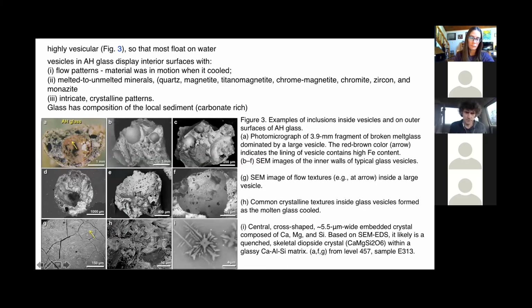What I would like to point out is that on some of the smooth surfaces, very often you can see a kind of lineation that shows there was actually motion of the fluid at the time of solidification. In some of these vesicles you can see coarse crystals growing, probably when the melt was evaporating; there was a lot of gas, and from the gas you could form crystals. We can also see quench diopside crystals that formed on some of these surfaces.